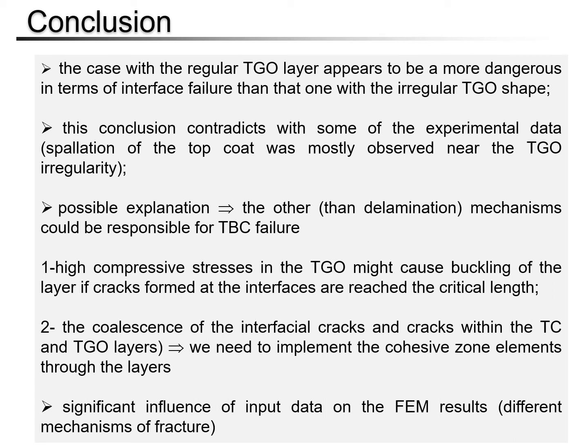As a possible explanation, mechanisms other than delamination could be responsible for TBC failure. It may be high compressive stress in TGO that causes buckling of the layer if cracks formed at the interfaces reach the critical length, or, the second possibility, it may be the coalescence of the interfacial cracks and cracks within the TC and TGO layers. So we need to implement cohesive zone elements through the layers to understand these effects. And as usual, we highlight that significant influence of input data on the FEM result is observed. So we need to be really attentive to input data.